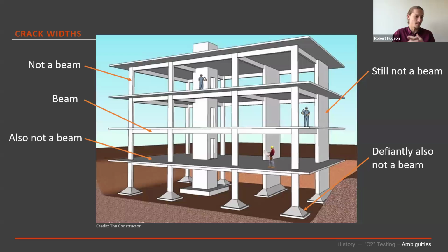One of the reasons we started playing around in the lab, trying to figure out how sensitive things like crack widths were to the end result, is because we wanted to understand how much this matters. And it's really sensitive. The outcome really matters on what your crack width is. So it's a really important thing as a designer to be aware of, that when you use these values, that is what you're allowing for. And that's what's been tested. And that's the testing that's behind the value that you're using.